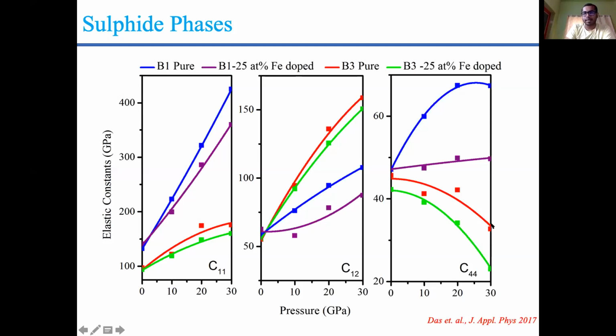So we can say that this B3 to B1 phase transition is purely shear driven, and the same transition for the iron doped case will happen earlier because of the softer C44. You can concentrate on this green line. But this C44 softening is also associated with the phonon modes. So this result leads us to investigate the lattice dynamical behavior of the system.